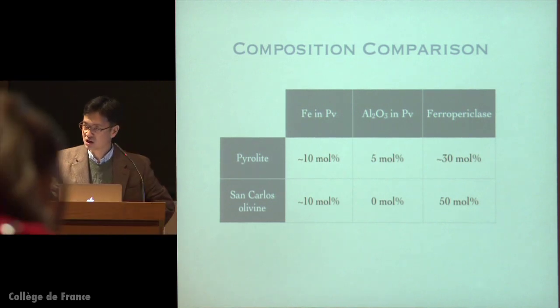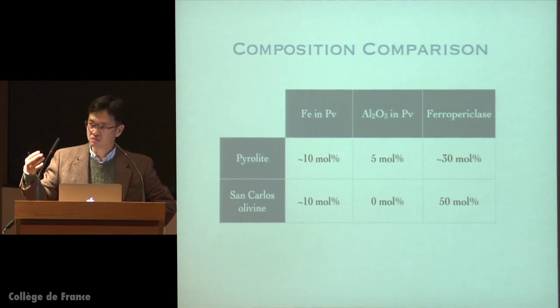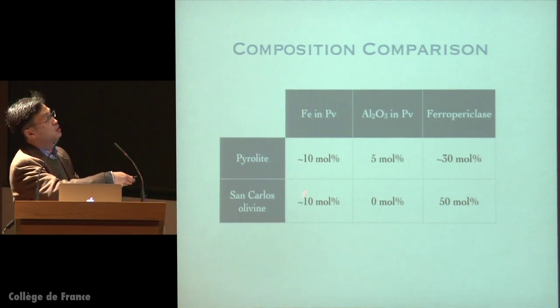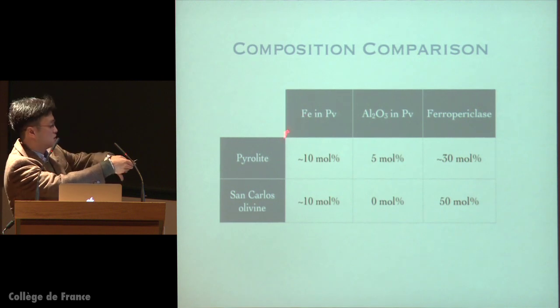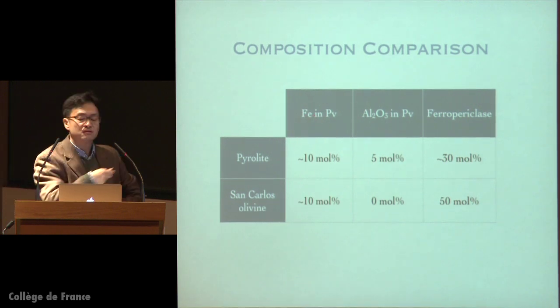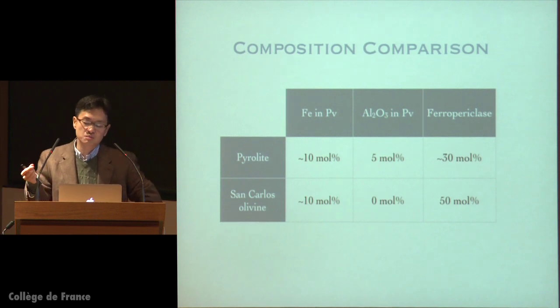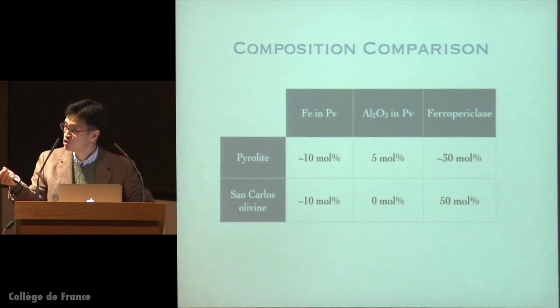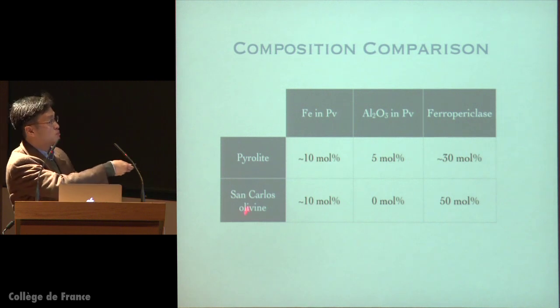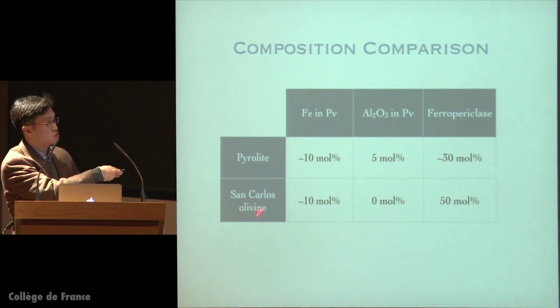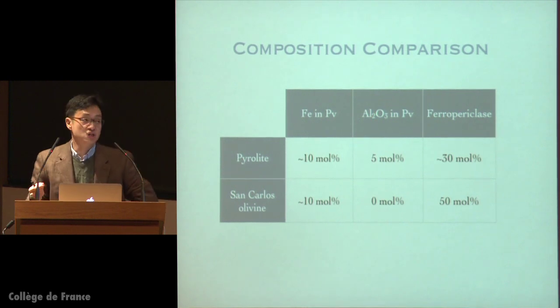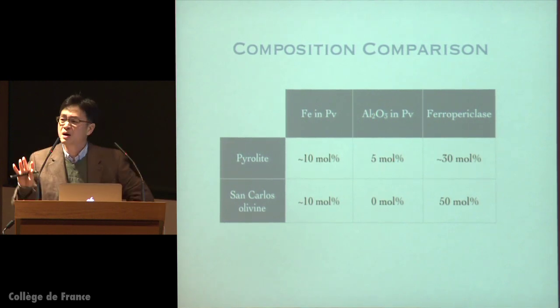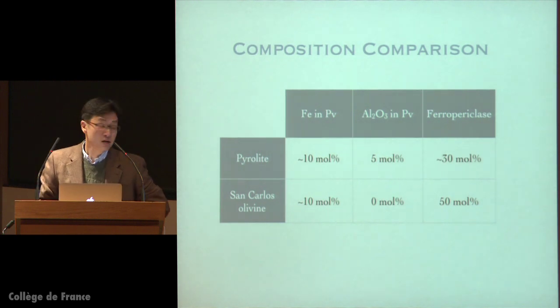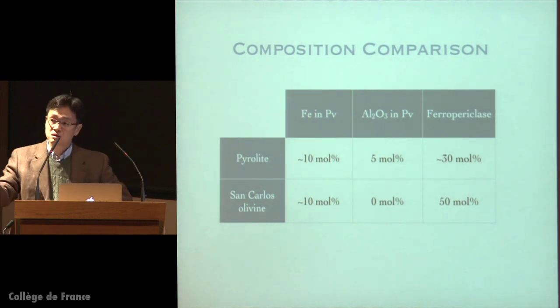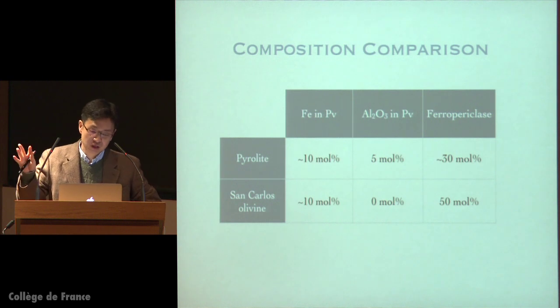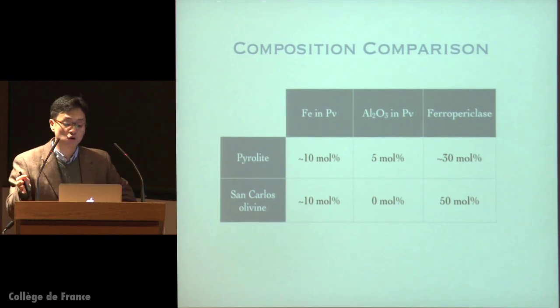So first, I'd like to compare the composition of pyrolite and San Carlos olivine, or if you wish, harzburgite composition, that's essentially olivine-dominated rock compositions. So if you look at the iron content expected for perovskite, in pyrolite, perovskite is supposed to contain about 10%, which doesn't change if you change the composition from pyrolite to San Carlos olivine. If you look at aluminum composition, pyrolite is supposed to contain about 5% of Al2O3, whereas San Carlos olivine doesn't allow perovskite to contain any aluminum because the starting material doesn't contain any aluminum in it.